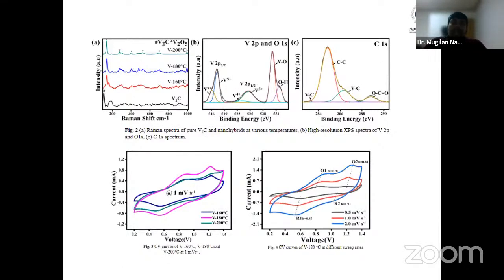I have taken XPS for my material. In XPS analysis we find the chemical structure and valence state of V2C and V2O5, and I found that it has a multi-oxidation state, with V5+ and V4+ states present. This multi-oxidation state leads to better electrochemical performance.